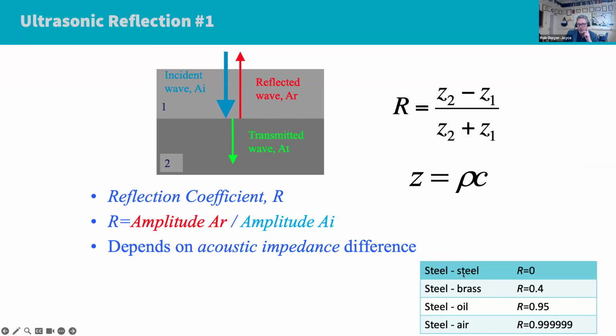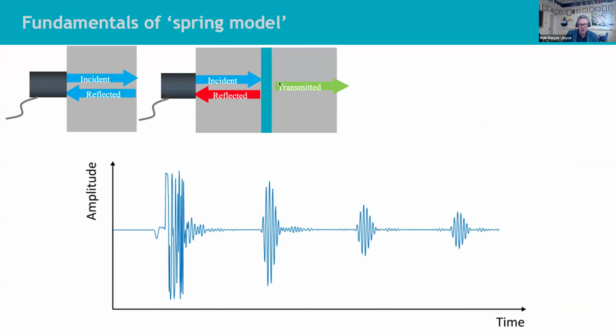So for example, if you have steel against steel, perfectly bonded, all the sound wave would pass through. If you've got steel against air, all the sound wave would be reflected back. And of course, what we've got is steel against an oil film. So we've got a reflection at this oil film here. You'd get one reflection at the front of the oil film and one reflection at the back of the oil film.